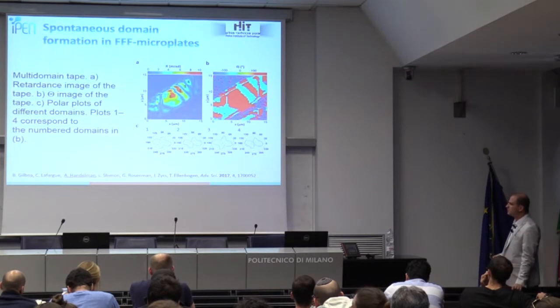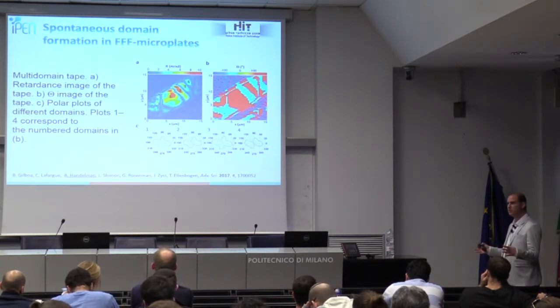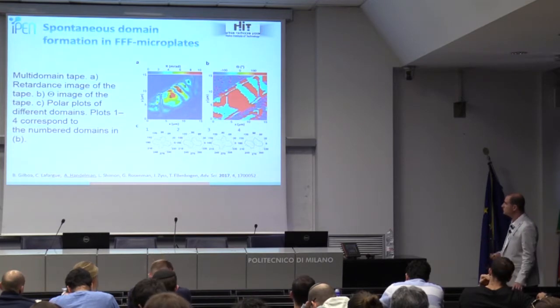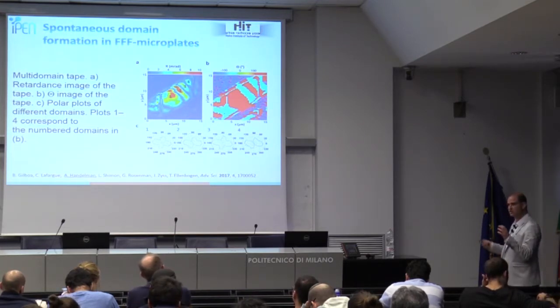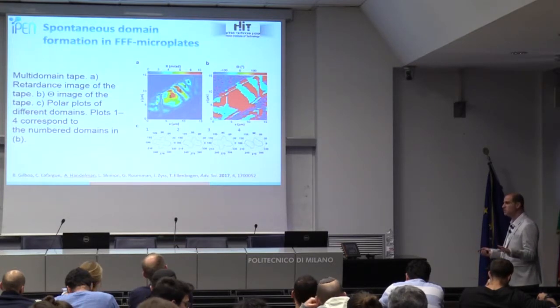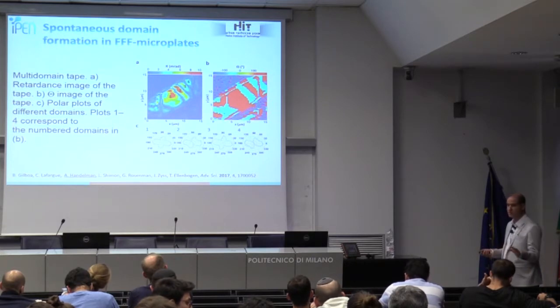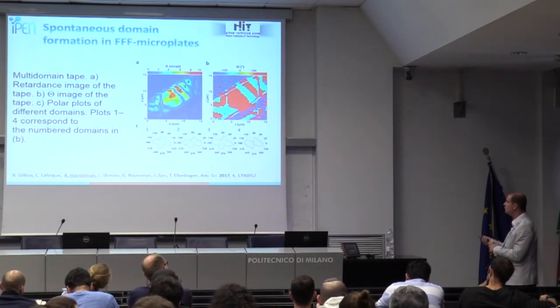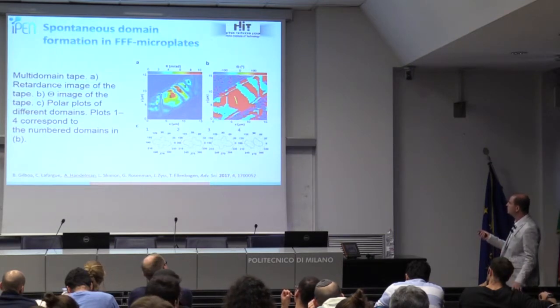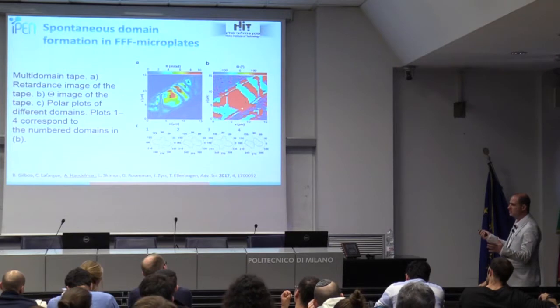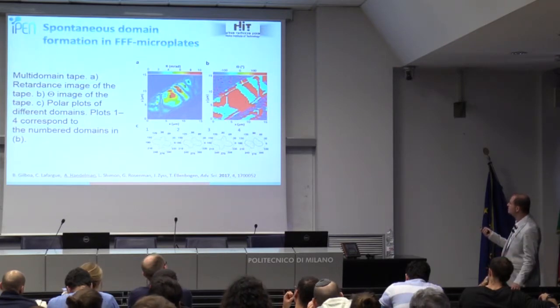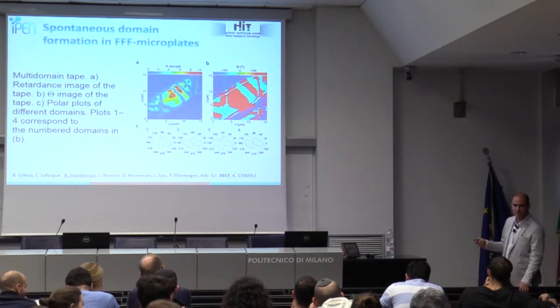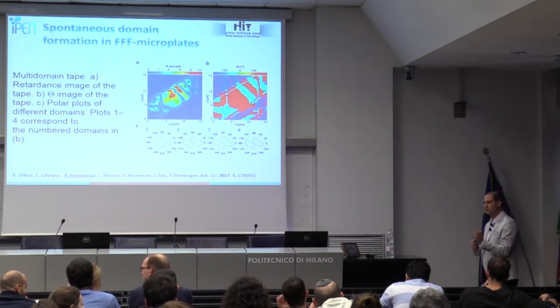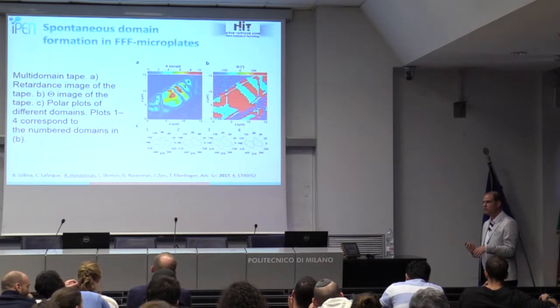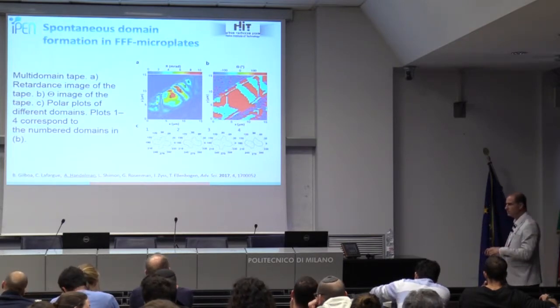And the most interesting thing that we discovered is that each kind of peptide, for example, here we measured the FFF microplates, contains multiple domains. This was a shock to us. We didn't expect it, and we don't understand why some microplates have all kinds of domains. You see here the different colors, here is red, here is, I don't know what color it is, I'm colorblind. And this is another red, okay? But not everything is red. So this means that there are multiple domains, so the polarization is different along the tubes or along the plate. So we don't understand why it happens, but it's interesting.